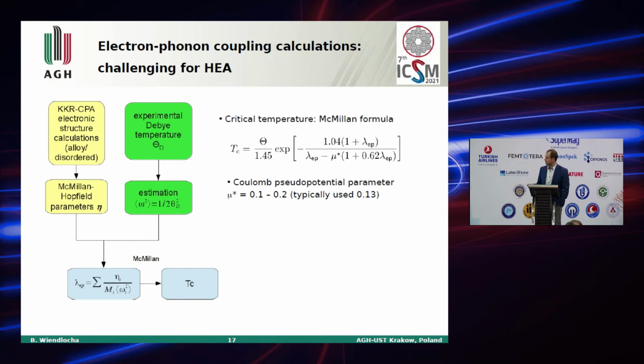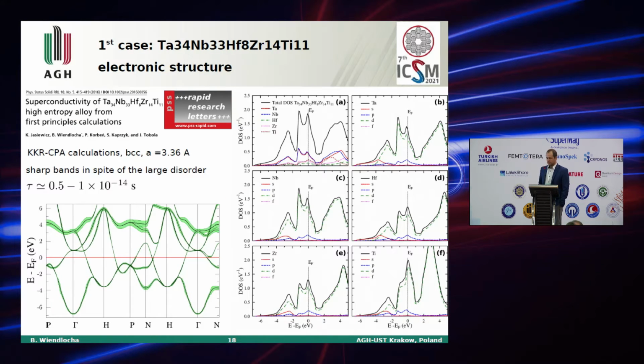So this is the summary of the setup used to calculate lambda for these materials. From KKR-CPA we get the McMillan-Hopfield parameters. From experiment we take the Debye temperature and then we calculate lambda, and if we know lambda we can calculate the critical temperature. Okay, so now let's move to results.